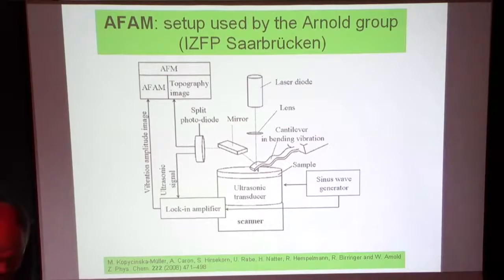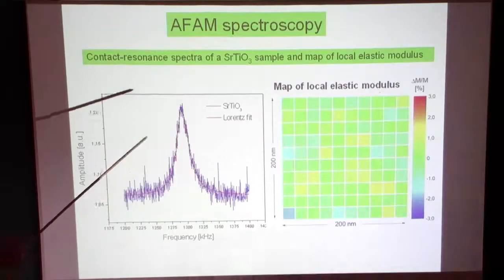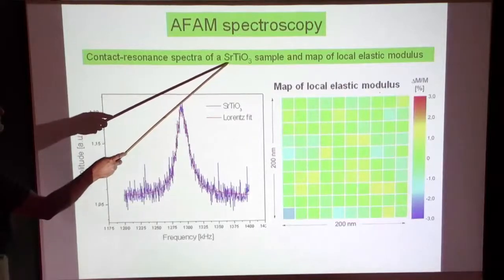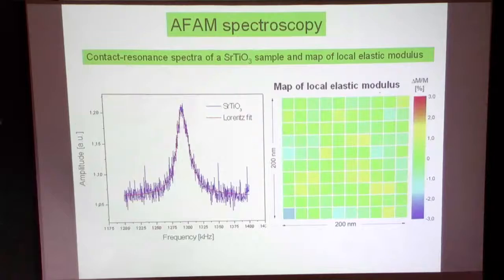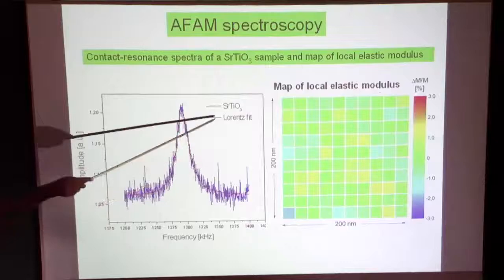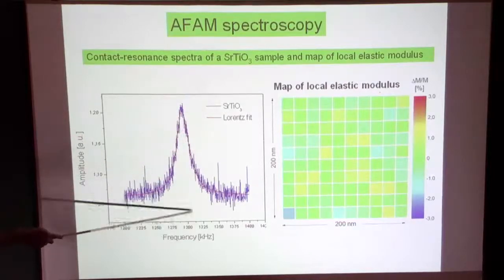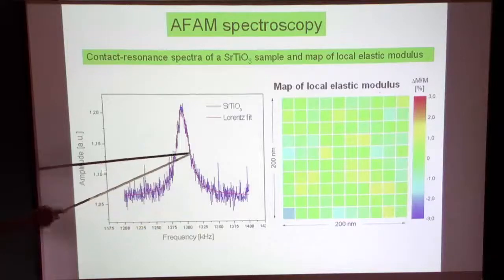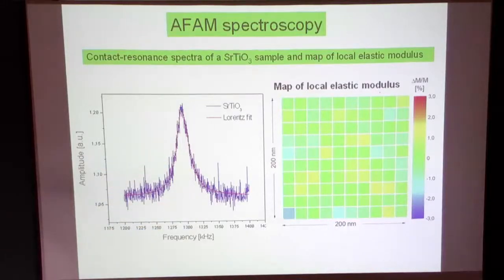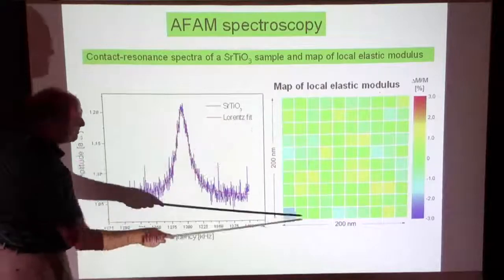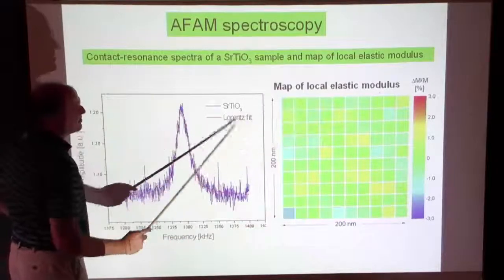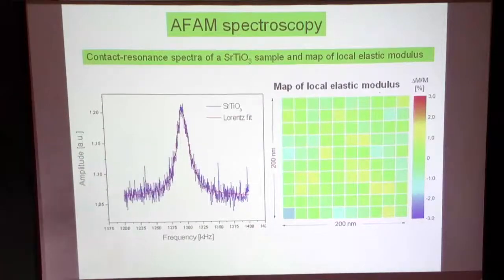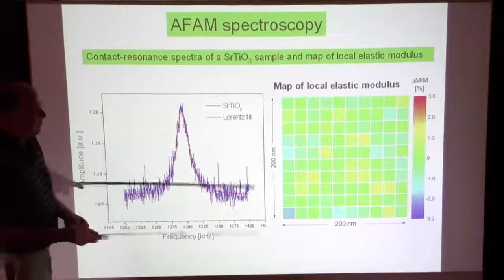We have this coarse-grained picture there, and the first system to test is actually the crystalline single crystal strontium titanate oxide system, and that's the excitation amplitude which you get, and you can fit it with a certain Lorentzian, and then you have a certain modulus which can be calculated from this frequency and the width, which gives you the losses more or less rather easily, and you can make a map. This is very coarse grain already, 200 by 200 nanometers, and you see the crystal, as it should be, is almost the same. So you have the same modulus, the same shear or bulk modulus, the components of those two get together into one elastic modulus that is rather homogeneous.